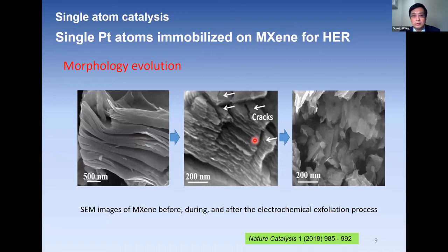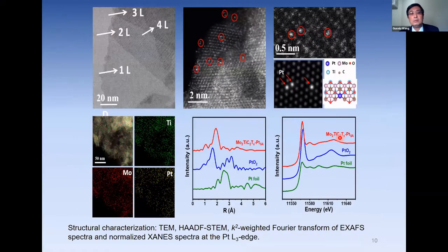And when you do the electrochemical exfoliation, gradually you can generate cracks and the MAX phase materials gradually delaminate, and finally you can obtain well exfoliated MXene nanosheets. So then we further use HRTEM and HAADF-STEM to characterize the obtained MXene nanosheets. You can obtain 1 layer, 2 layer, or multi-layer MXene nanosheets.